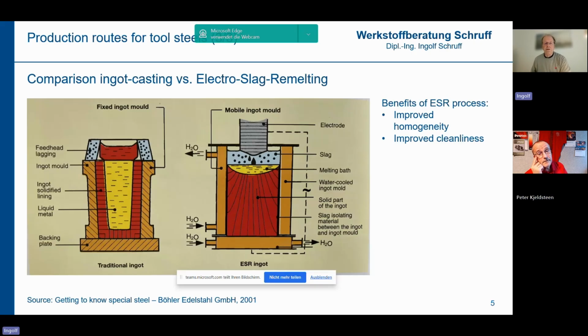The next effect is that we have the purification and the comparably homogeneous solidification. But we also have the beneficial effect that we can create larger cross sections than before with the electrode. That means we can, for example, melt a round ESR ingot with a diameter of approximately 1,000 millimeter from an electrode with 750 millimeters diameter. So we can increase the achievable cross-section of the steel. That is necessary to fulfill the dimensional demands which we have nowadays.